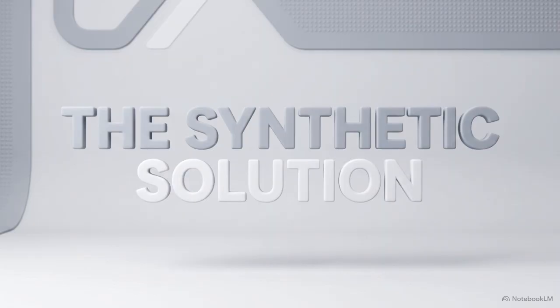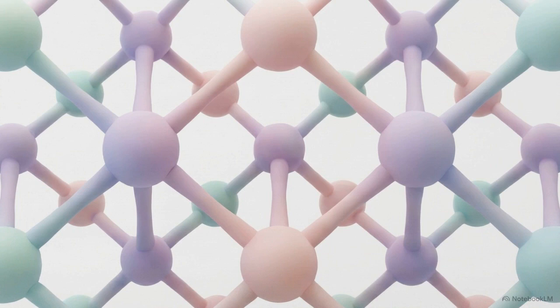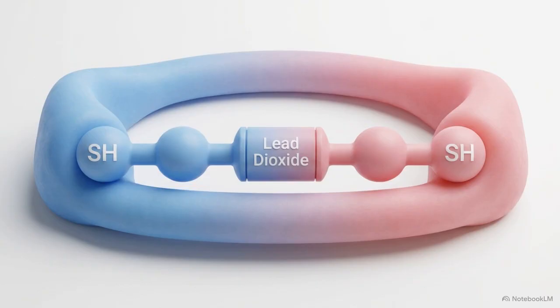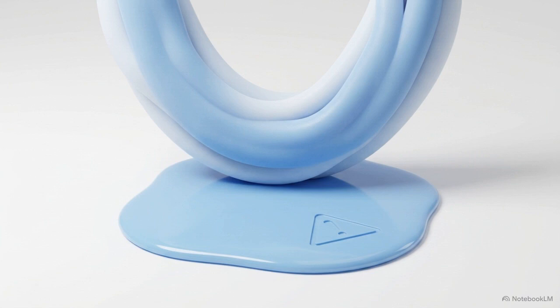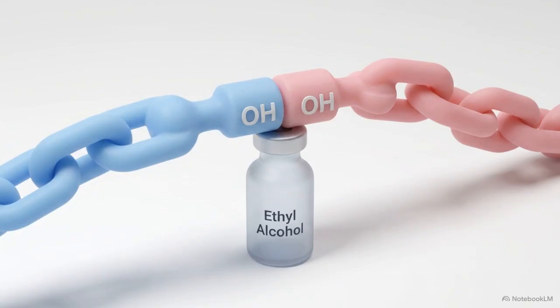To solve the severe instability of hydrocolloids, material science developed non-aqueous elastomers. Instead of relying on a water dispersion phase, these materials utilize robust synthetic polymerization reactions. The first elastomers were polysulfides. They achieve massive tear strength by oxidizing terminal mercaptan groups with lead dioxide. However, this specific chain-lengthening reaction produces water as a chemical byproduct. Condensation silicones attempt a different chemistry. They cross-link hydroxyl-terminated polymers, but this specific reaction releases ethyl alcohol as a byproduct.